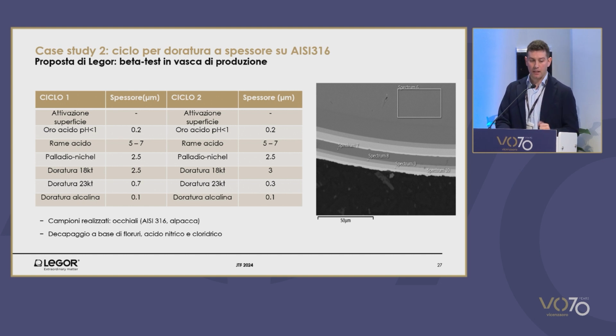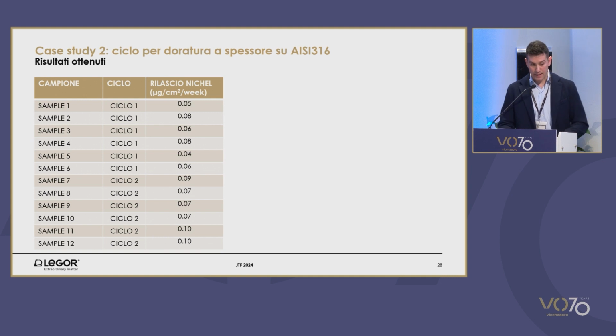The gold plating has been done with 18-karat gold for most of the gold being layered, and a 23-karat gold additional layer to make a more effective barrier, and an alkaline addition to get to the color that the customer was requesting. AISI 316 was used, and treatment has been used with chlorides and acidic substances. The test performed showed that the release amounts of nickel are well below the threshold limits, less than 0.5.